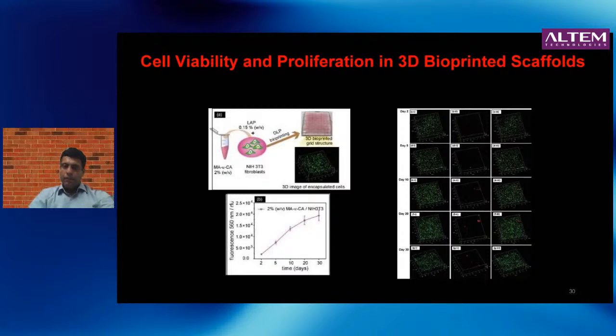Okay, and I should emphasize that one has to play with the printing parameters in terms of the laser power and the time required for curing each layer. All of those, of course, have to be optimized. If you under-cure it, then the scaffold will fall apart too quickly. If you over-cure it, sometimes that can harm the cells. So one has to optimize the printing parameters so that you can get the best bioprinting conditions where you get stable scaffolds, but the cell viability and growth is not compromised.